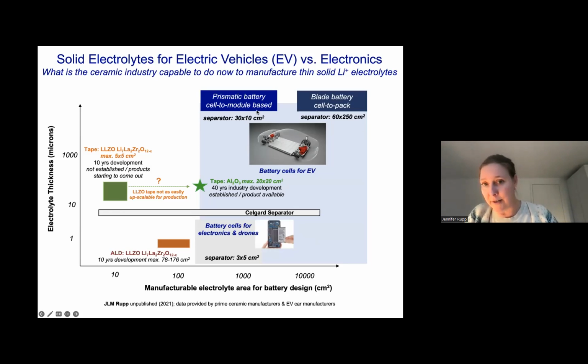In a car, you need about 30 by 10 square centimeters of a crack-free ceramic if you want to make a solid-state battery that's really upscaled to this area. And that's actually not so easy to do. The current Celgard separators are wonderful polymer materials because you can work with them over the whole range of areas. So they're very easily area upscalable, and they have a quite low thickness, which is around 10 microns.